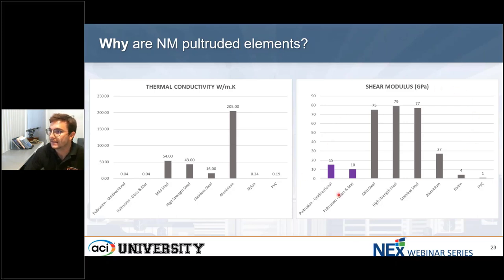This slide puts you in context on shear properties that my colleague Ehsan will talk about. Since pultruded elements have all fibers aligned unidirectionally through the pultrusion process, they are very strong in that direction, but the shear capacity is lower — it's one-fifth of that of steel. This is a critical property specifically for connections, where shear plays a critical role.